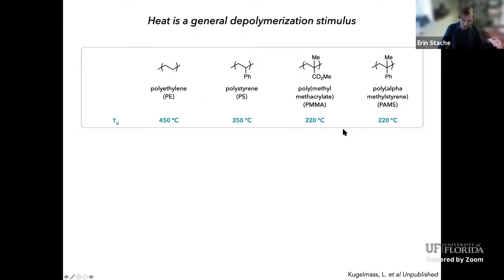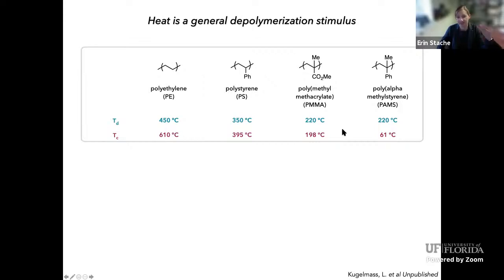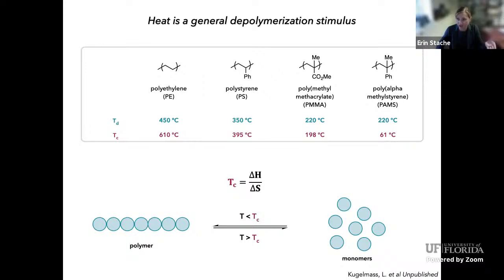Now, the other thing to think about in polymers is the thermodynamics, and this is the ceiling temperature. So all polymers are unstable at a certain elevated temperature. Most polymers are unstable at an elevated temperature. And so the ceiling temperature is the thermodynamic principle for actually turning monomer into polymer. Polymerizations are driven by enthalpy, but they're going against entropy by stringing all of these small molecules together to make a long chain polymer. And so at a certain temperature, that entropic cost will outcompete the enthalpic benefit, and you can actually push the polymerization towards depolymerization. So you can think about this: if you're below the ceiling temperature, you can make polymer, and if you're above the ceiling temperature, you can depolymerize it to monomer. Now, these are absolute ceiling temperatures. There are actually an infinite number of ceiling temperatures for every polymer, depends on concentration. But at these temperatures, you cannot push monomer towards polymer.